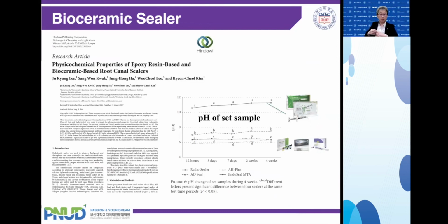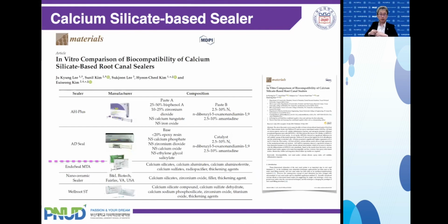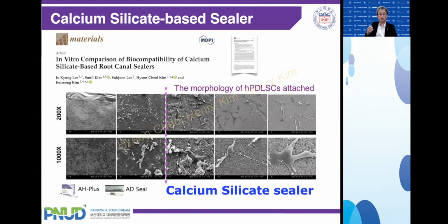Here is another study from my group comparing 2 epoxy sealers with 3 CS sealers. We checked how much affinity those calcium silicate sealers have to human PDL cells. As you see here, there is no cell attachment on the epoxy resin sealer on the left side, but on the right side, the cells show good attachment on the calcium silicate sealers.